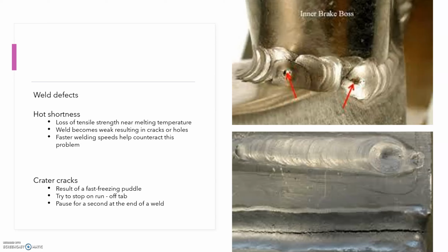The puddle freezes very fast, so if you do not have enough filler material at the end of a weld, shrinkage pulls the end of the weld apart, leaving a crater. You can pause at the end of a weld and then stop, or you can incorporate runoff tabs to finish the weld off.